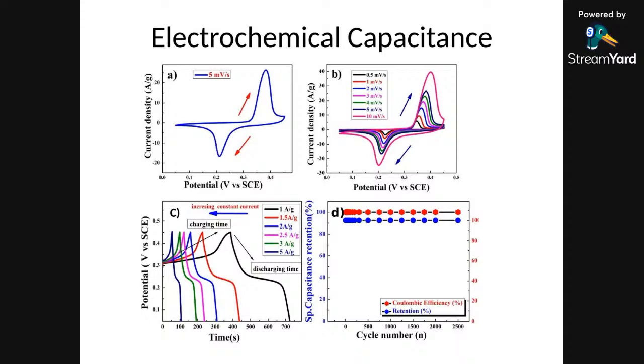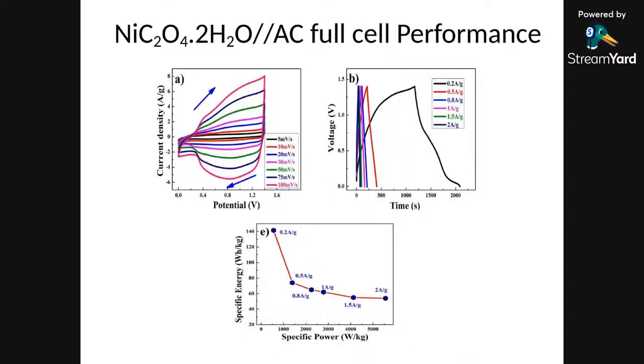And we are getting, at much higher current, up to 5 ampere per gram current rate, we are able to do this intercalation. And the specific capacitance retention was very high. So what we thought, because the nickel oxalate single electrode had shown a much intercalative kind of property.